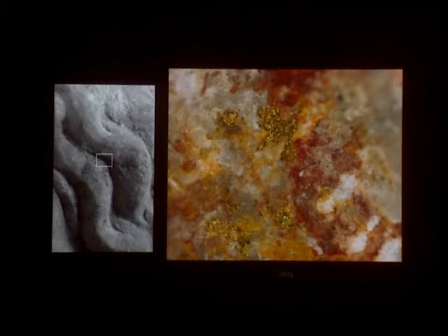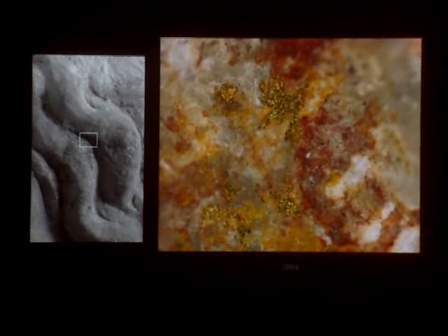In polarized light microscopy, the red ochre on top of the gold leaf is morphologically similar to the red ochre found on the fillet, eyes, eyebrows, and mouth — so presumably all are contemporaneous. How should we interpret this red ochre pigment applied on top of the gold leaf? There is no indication that it indicates a later campaign of polychromy. Rather, it appears to be a preserved red overglaze painted on top of the gilding to impart definition and variation to its golden surface — perhaps delineating individual locks of hair, as often found in red glazes on top of gilded hair in medieval sculpture. This red overglaze reminds us that ancient gilded surfaces were not monochromatic and uniform, but were themselves embellished with a range of subtle effects.